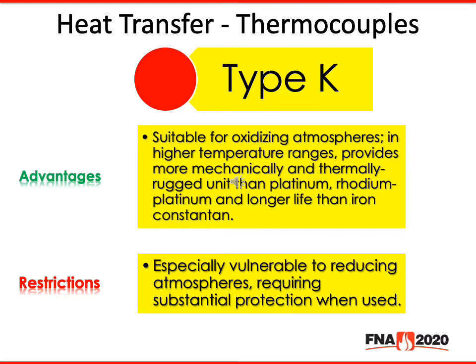As with any thermocouple, type K thermocouples have their advantages and restrictions. Some advantages: they're suitable for oxidizing atmospheres. In higher temperature ranges, they provide a more mechanically and thermally rugged unit than platinum, rhodium-platinum, and have a longer life than iron constantan. Some restrictions: they are especially vulnerable to reducing atmospheres, requiring substantial protection when used.